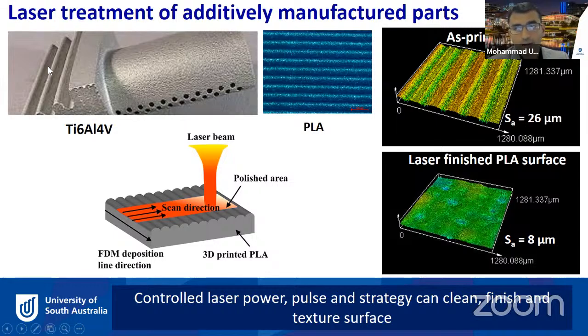For example, this is one example of a titanium alloy manufactured by the additive manufacturing process. If you apply laser finishing, which is basically applying laser energy onto the surface, you can make the rough surface very smooth. So what happens here? The laser melts the small peaks and the droplets on the surface, and the melted material flows into the valleys and makes the surface very, very smooth.